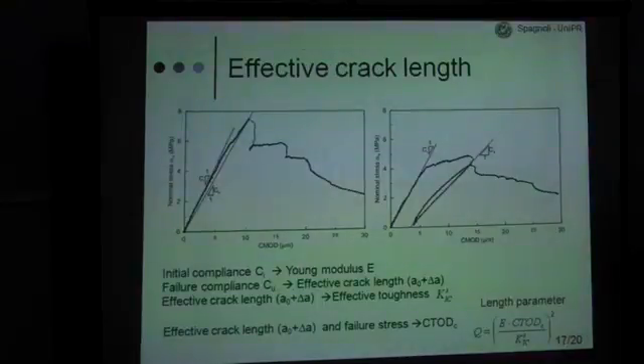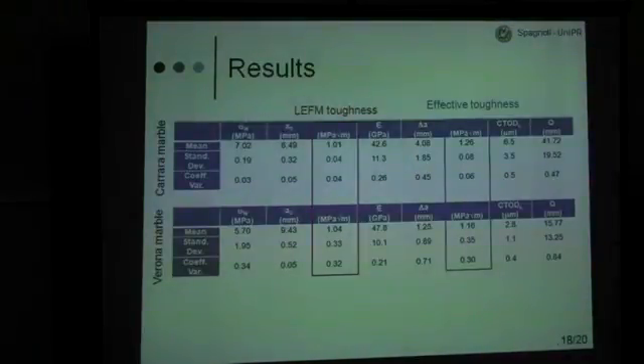Okay, so these are two curves from the results that I showed you before. From the initial compliance you work out the Young modulus, then from the failure compliance you obtain the effective crack length, and from the effective crack length you work out the effective toughness. And finally you can have a measure of the blunting of the crack, what is called the CTOD critical, and eventually the length parameter Q can be calculated. Just a couple of slides.